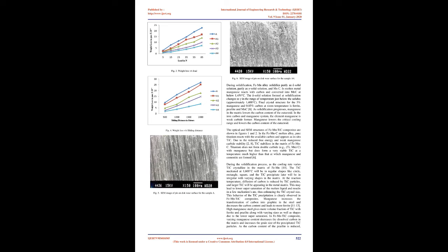In the iron carbon and manganese system, the element manganese is a weak carbide former. Manganese lowers the critical cooling range and lowers the carbon content of the eutectoid. The optical and SEM structures of Fe-Mn-TiC composites are shown in figures 1 and 2. In the Fe-Mn-C molten alloy, pure titanium reacts with the available carbon and appears as in-situ TiC.